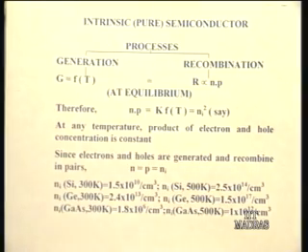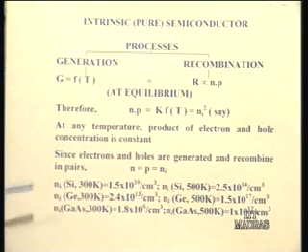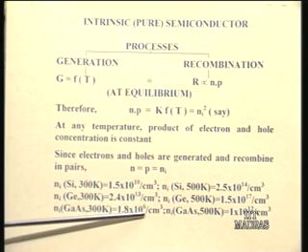The intrinsic carrier concentration ni depends on both the material and temperature. For silicon at room temperature it is 1.5×10¹⁰ per cm³, but at 500 K it increases by about 4 orders of magnitude. For germanium, which has a lower band gap, ni is 10¹³ per cm³ at room temperature — again about 4 orders of magnitude higher at elevated temperature. For gallium arsenide, with its high band gap of 1.42 eV compared to silicon's 1.1 eV, ni is only 10⁶ per cm³.